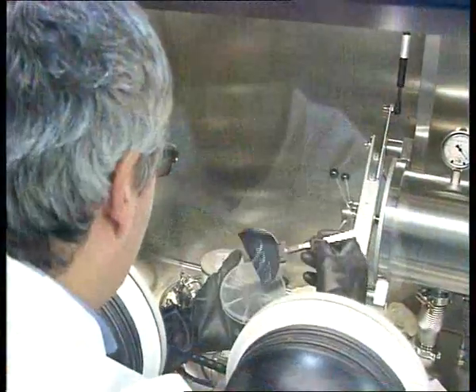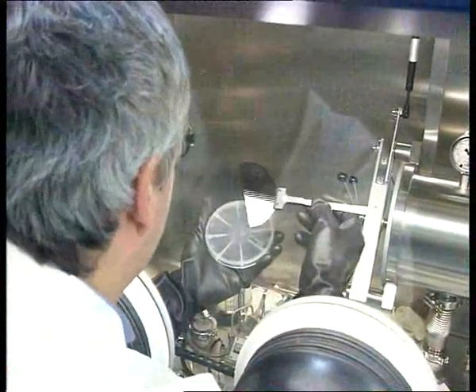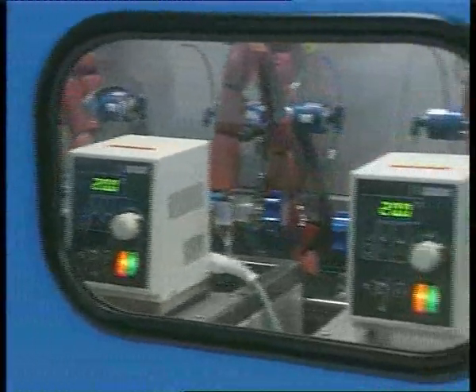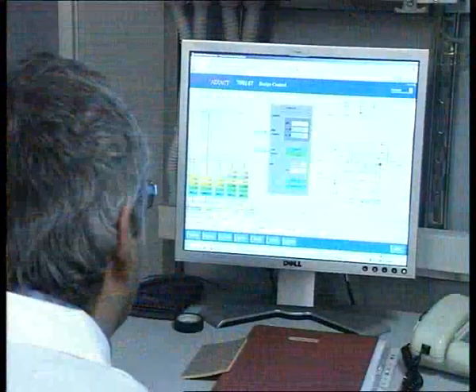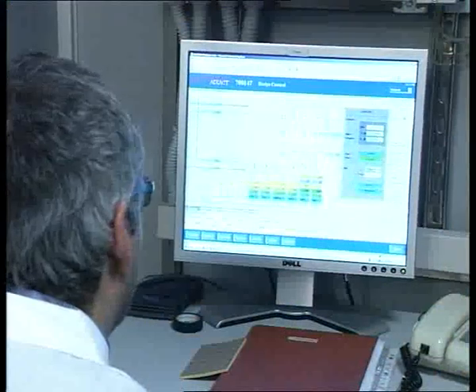During the project, a laboratory fully devoted to the deposition and characterization of chalcogenide materials was set up at MDM. In particular, an Aixtron MOCVD reactor, which does not use dangerous gases, was installed. The equipment was dedicated to the growth of thin germanium, antimony and tellurium alloy layers on 4-inch substrates.